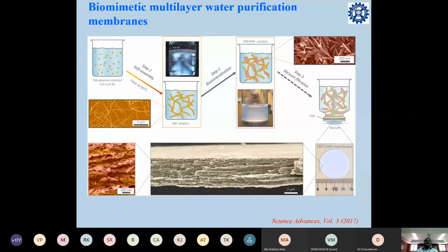Okay. The next one is different from other types of membranes. So this is biomimetic membranes. So here there are some biomimetic components made into multi-layers. They take a silk aqueous solution, and then they make it into a silk nanofiber (SNF) solution by heating at 60 degrees Celsius. So that means the individual silk particles aggregate to form this silk nanofiber solution, and then they do biomineralization with hydroxyapatite. So this hydroxyapatite is nothing but a phosphate mineral, which is the main constituent in our bones.